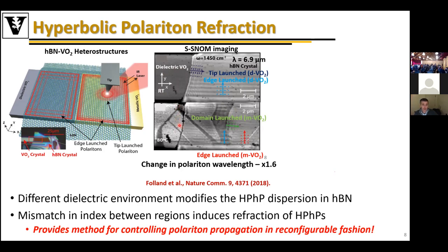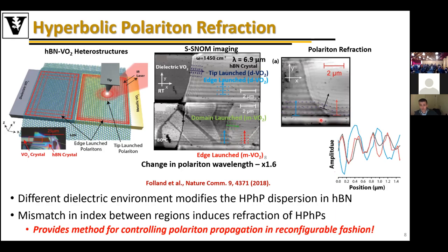These bright areas correspond to the metallic, dark regions to the dielectric phases. And what you can find is if I look at the polaritonic wavelength in the boron nitride as it's propagating over these different regions, these are quite different, by about a factor of 1.6. And thus, if I launch a polariton off this edge of the crystal into the boron nitride, but then it comes to a domain boundary where it's propagating from the dielectric into the metallic phase, because of that mismatch in the wave vector, you get refraction of the polariton. And we were able to demonstrate that this follows Snell's law, thus giving rise to the potential to use all of